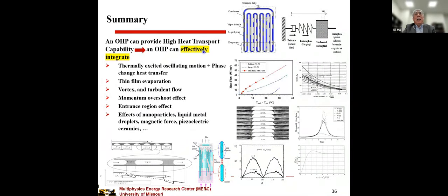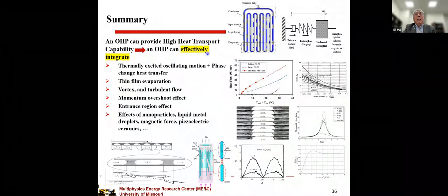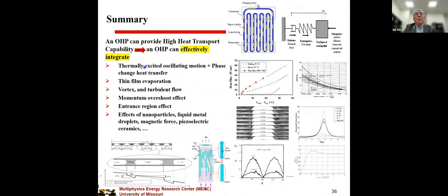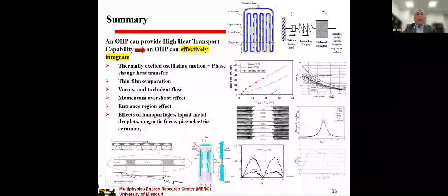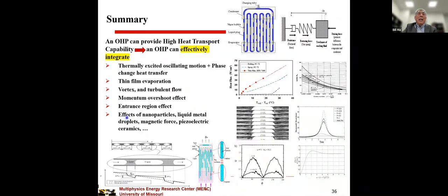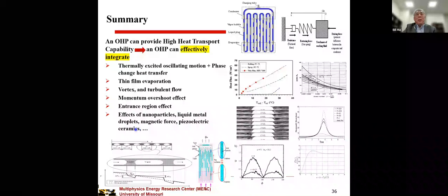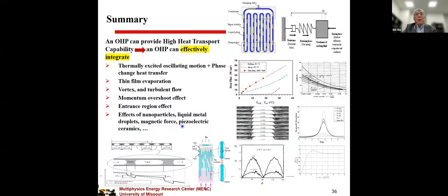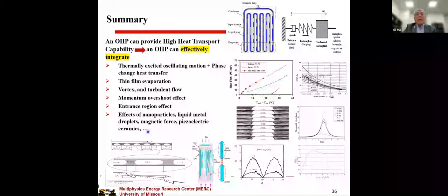The oscillating heat pipe can provide very high heat transport capability. The reason is that it can effectively integrate thermally excited oscillating motion, phase change heat transfer, evaporation, condensation, thin film evaporation, vortex, turbulent flow, momentum overshoot, and entry region effects. In addition, we can add nanoparticles, liquid metal droplets, magnetic force, piezoelectric, ceramic, and many others.